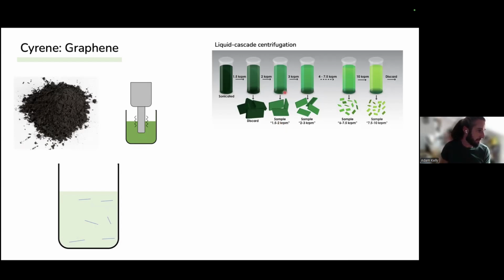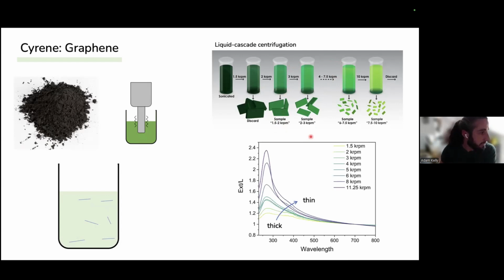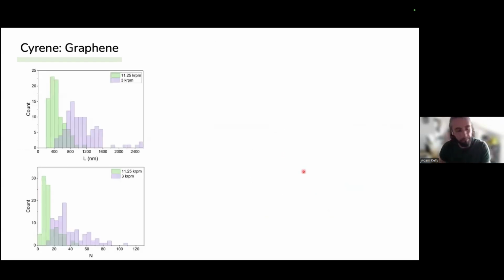This will be sample 1, for example. Then we take the supernatant and we continue this process up, and we iteratively get progressively smaller and thinner nanosheets. So we did this for the graphene exfoliated in Cyrene. This is a UV-vis spectra here where we can see that the low speed centrifugation produces thick nanosheets, which is related to the relationship here between the ratio of the peak to the long wavelength plateau. And we see that as the centrifugation speed increases, we get thinner and thinner nanosheets.